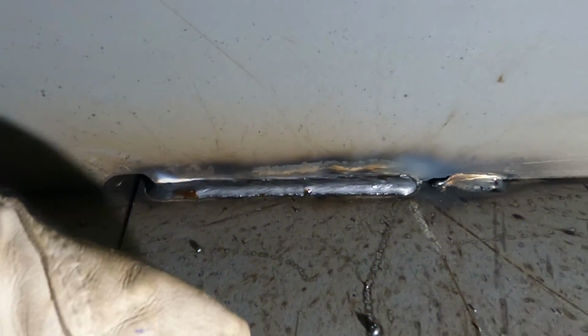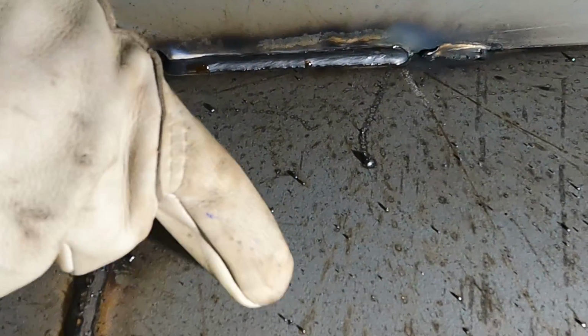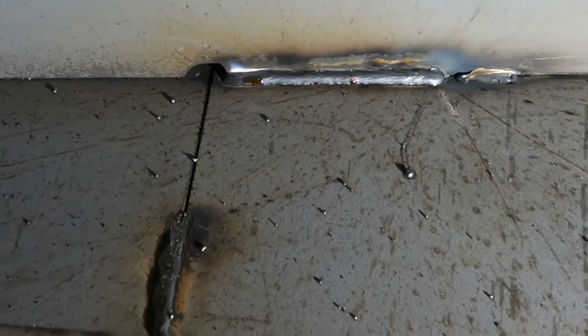You can see kind of the hot balls all over the plate where it just spattered all over the place. And that hump in the middle of the puddle really didn't get a chance to form out like it's supposed to. If you see the plate here, you can see all the blowback, the chunks of metal just flying out, because we're getting too much wire in there.